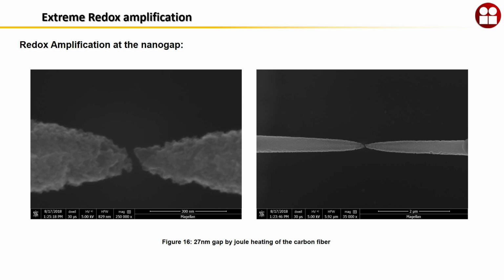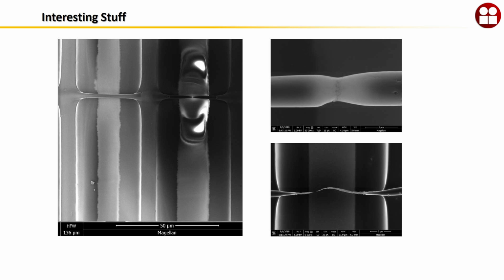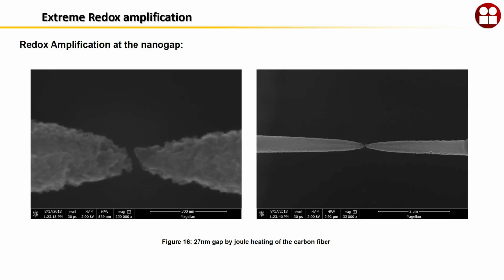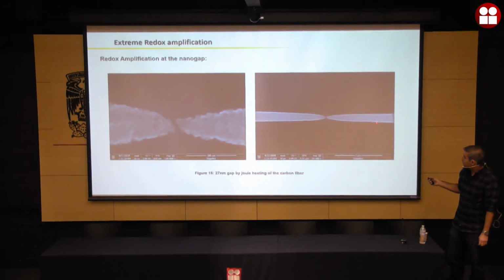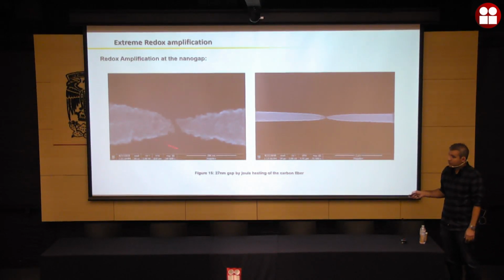This gap is about 27 nanometers. It is still way smaller than the dimension of the diffusion layer, and the whole geometry is going to work for me because right now I am in that diffusion layer. Unfortunately, I don't have any experimental data because we got this working almost 10 days ago, last week. So this was a lucky image that we got, and by the time I go back to California, I have to start running experiments in nano gaps and quantify this.